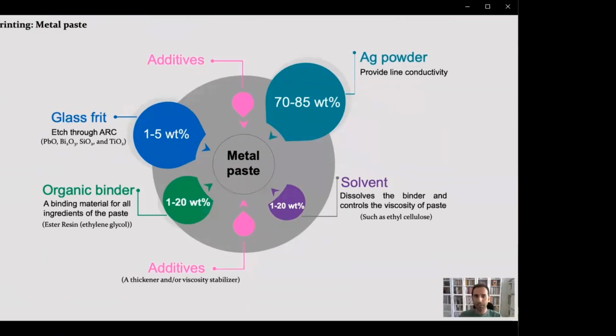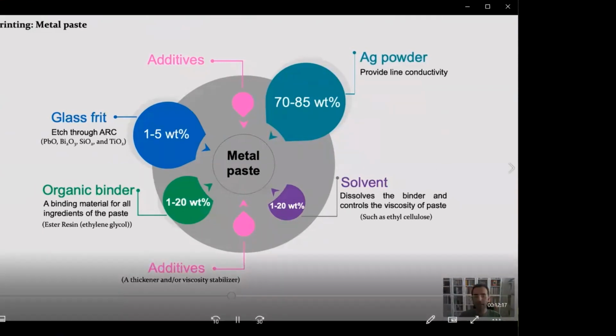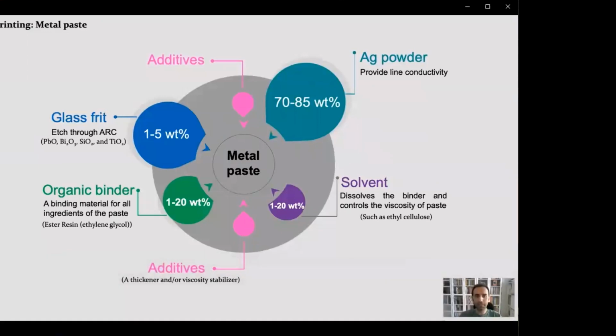Metal particles provide the conductivity since they are the metal bulk. Glass frit etches through the anti-reflection coating layer during contact firing. Because the paste is printed on the ARC layer and the metal should make a contact with the emitter, the ARC layer should be etched. Organics and solvents, on the other hand, are accounted for the rheology of the paste, like how viscous it is or its printability. For the backside, thin aluminum paste is used and screen printed on the backside.